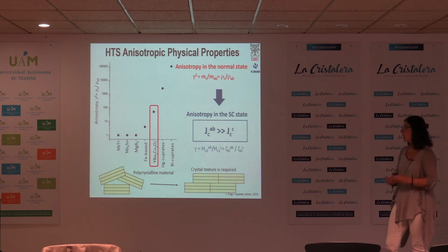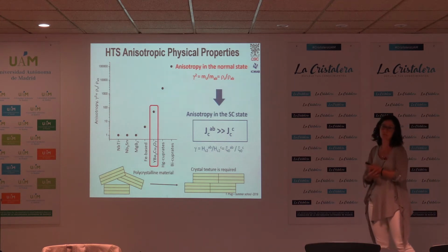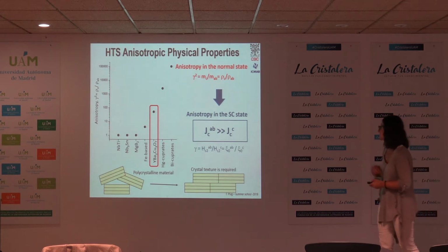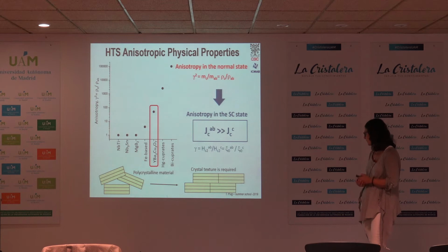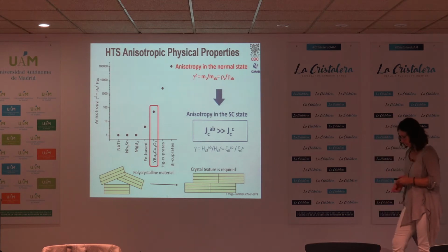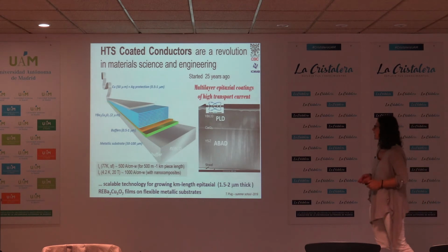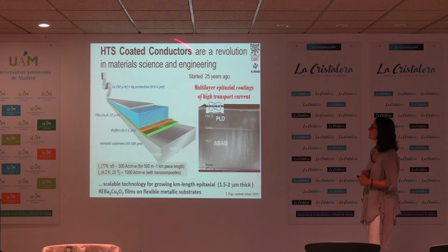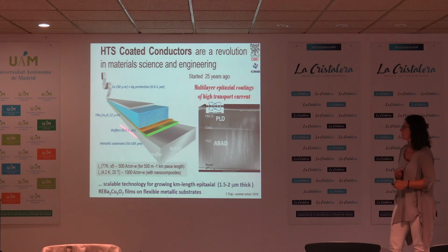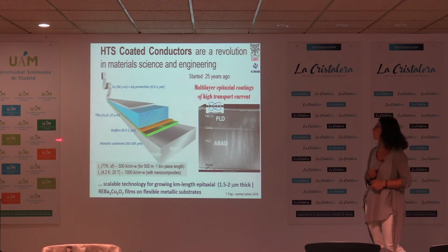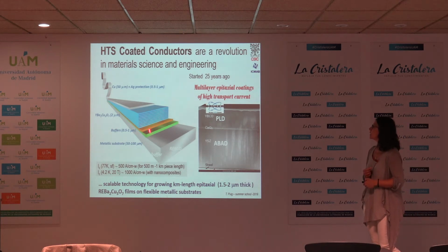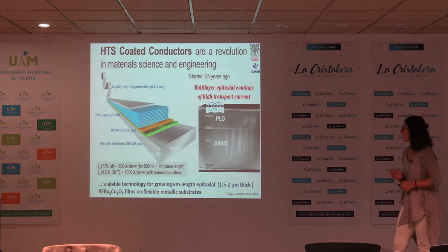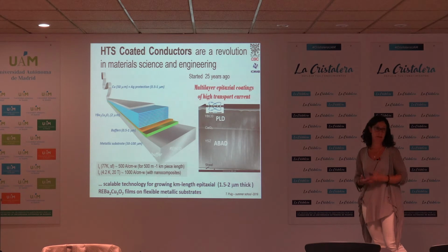And therefore, if we want to do wires and we don't want to do kilometer length, we have to do thin film technology on kilometer length, which is where materials had to be strongly improved and a lot of effort being done. In fact, the idea at the end is to put these materials in the form of coated conductors. That means that we have a metallic substrate, thin substrate, on top of which we put some buffer layers in order to match the substrate to the superconducting layer. Then we put the superconducting layer on top, and then silver or copper protection. So that means that we have to do all this multi-layer technology for thin film in kilometer length.